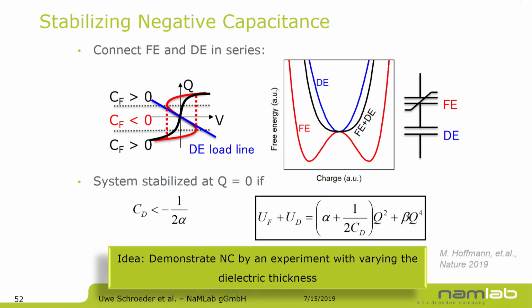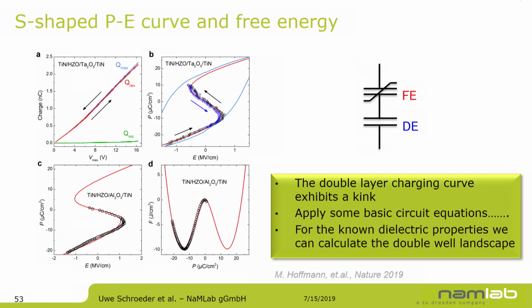Our idea, and Michael Hoffmann was working on the topic, was to go through a series of capacitor structures with different thicknesses, so that at some point we should see this effect. If there's a negative capacitance and you measure the charge on the overall structure, at some point there should be a change in the charge measured on the overall system, and that's what you can see here. There's a small kink here, and if you calculate from the charge versus voltage to the polarization versus the field, you would follow a kind of S-shaped curve.